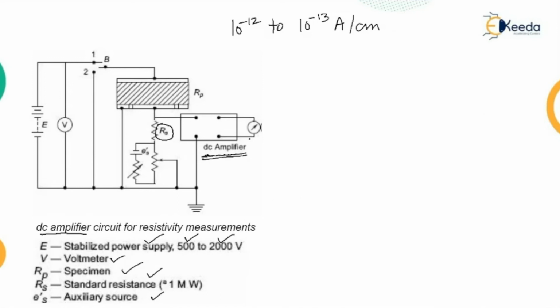Any AC voltage appearing across the standard resistance RS is amplified only by the net gain of the amplifier, which is small. Using a recording meter after the DC amplifier in this arrangement, the volt ampere time curves for long durations of the order of several hours can be obtained. This information is essential to determine relaxation time at low frequencies or with DC. So this is one kind of DC amplifier circuit.